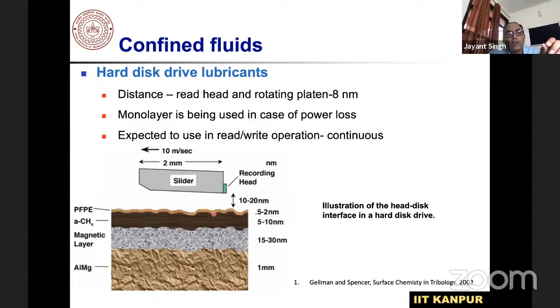So let me tell you the relevance of such work in experiment and in industry. This is a simple fluid, or lubricant, which is used in a hard disk on top of the disk. The slider, which is the recording head, reads the data which you record on your hard disk, and there is a rotating disk used to check the read and write operation continuously. This is just an illustration. Now, due to this continuous operation, if it gets dry, then a lot of heat will be generated, and that can create problems. So it is important to have a lubricant which doesn't dry up. This gap is around 10 to 20 nanometer, so it plays an important role to understand the liquid nature of the lubricant in this condition, and to understand the condition for the liquid-to-solid transition for such a system.